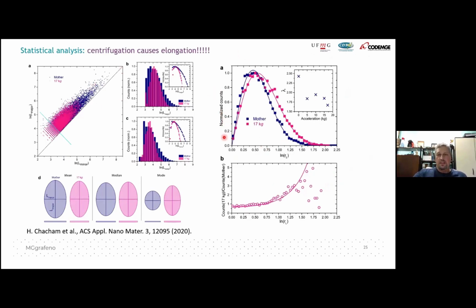Another thing, this was really surprising. If you are doing this type of analysis, we can also plot another type of ratio, which is the ratio between the major length and the minor length. Of course you can make a lot of statistics here, but the main point is that this ratio gets larger if you do the centrifugation. In other words, the centrifugation causes some kind of elongation in your graphene particles. More elongated particles come if you increase the acceleration.